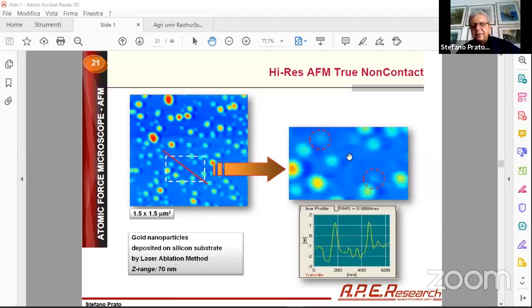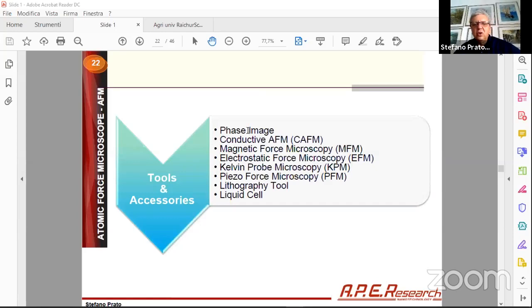So it's very, very difficult to catch 2 nanometer gold nanoparticles because they are very, very reactive, okay? To do this, you need an AFM, not only an AFM, but an AFM with an excellent sensitivity. Okay, now I will show you, maybe I will not go too much into the detail, otherwise it takes too much time.